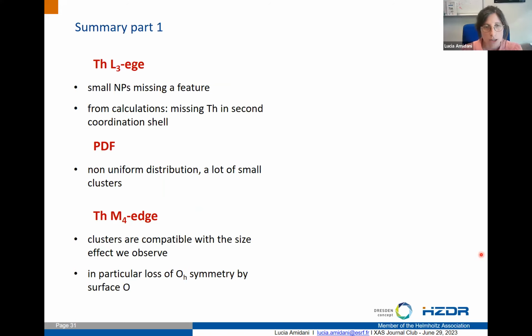So actually, in this example that I showed you as a summary, we have small nanoparticles that in the L3 edge show a feature missing, and we were able initially from calculations to ascribe this missing feature to the absence of thorium in the second coordination shell. And we had the hint that we really need to lower those numbers a lot to get this to disappear. The PDF really got us towards a better characterization of this distribution of nanoparticles and highlighted the presence of those small clusters that were then necessary to explain indeed the data we saw at the M edge. And the M edge really seems to be sensitive to those clusters and to the symmetry of the oxygen at the surface.